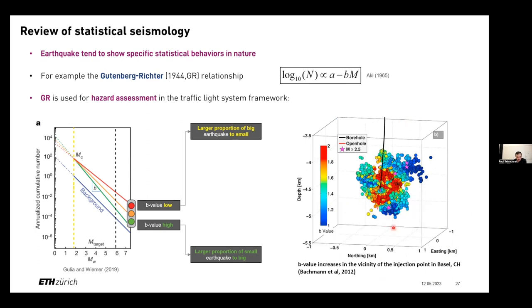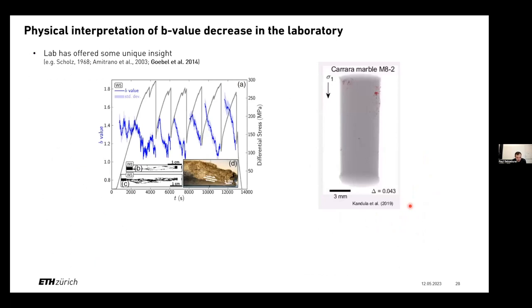They have also seen this, and this is just one example, in the vicinity of an injection well in Basel. They could also see the B value increase essentially at the injection well, but it had some interesting spatio-temporal patterns. Has this been observed in the lab? Yes, it has. There's a numerous amount of laboratory studies, and I'll highlight three that you should read if you're interested. The Schultz study that I referred to before, and Amitrano in 2003 and his co-authors have a nice study in JGR. What I'm showing you here is another study from Thomas Goebel that looked at the increase of differential stress and the B value from similar acoustic emission sensors, which would drop in general leading up to this stress drop.